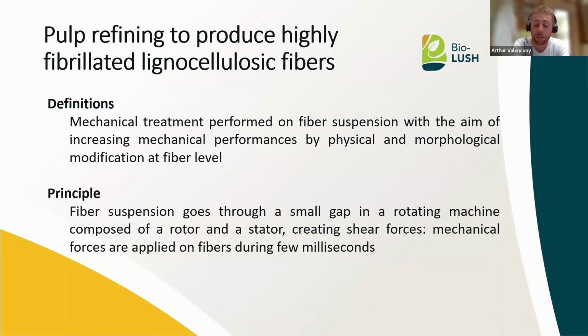So an interesting and important step to improve the properties of this pulp is the refining. Refining is a mechanical treatment which is performed on a fiber suspension, and it will increase the mechanical performance by modifying the physical and morphological properties at the fiber level. The principle is that, for all types of refiner, the pulp goes into a small gap where we have shear forces, and these mechanical forces modify the fibers during only a few milliseconds, and improve fiber properties such as mechanical ones or optical ones.